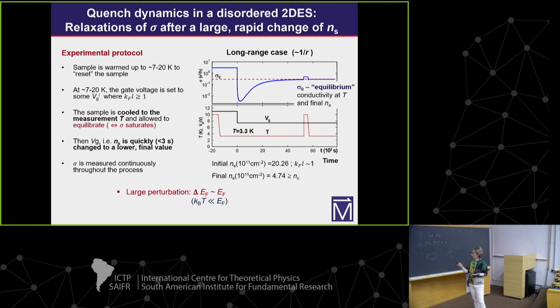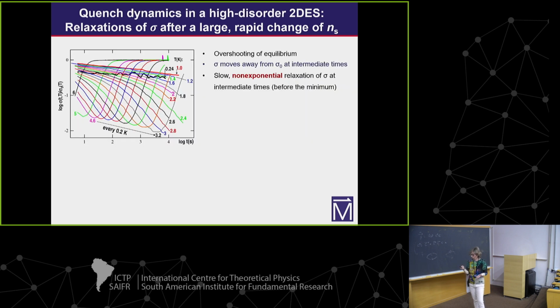Now you can repeat the same procedure using the same densities for different temperatures, and you end up with a bunch of curves. Note that here we are plotting this ratio, deviation of conductivity from this final equilibrium value for that temperature. So on this logarithmic scale, 0 is the equilibrium conductivity for each of these curves.